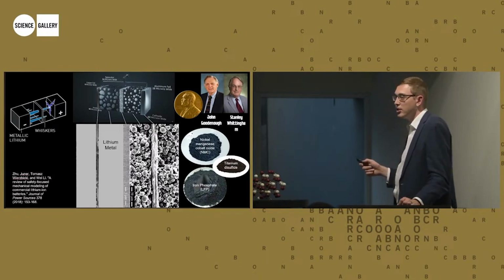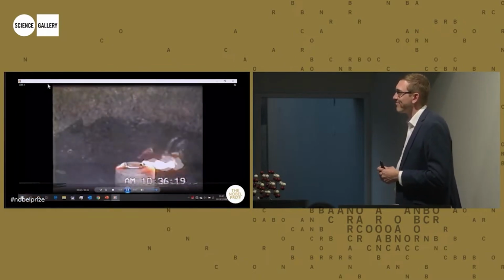And so what happened next in the 90s was, so the way that they would fail is that the metallic lithium would grow these little whiskers called dendrites, and these whiskers would puncture the plastic separator and would short the battery, and then that would be the failure of the battery. They would explode violently. This here is actually a video taken by Akira Yoshino of a lithium battery with a metallic lithium anode. Not good. Fire. Much damage.